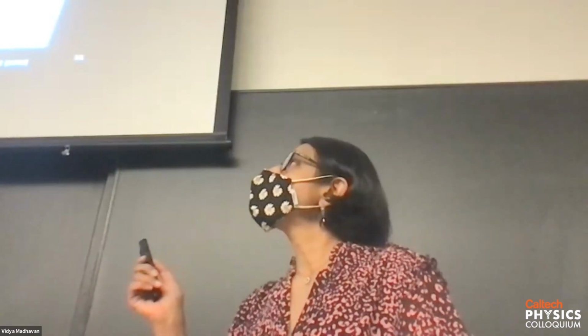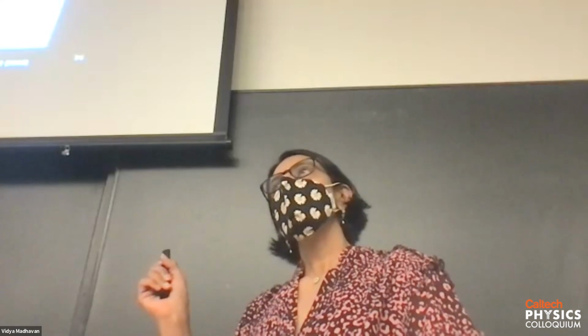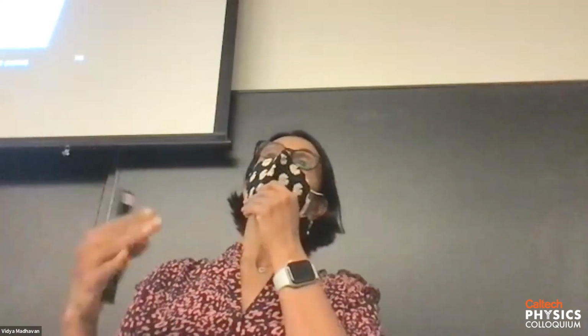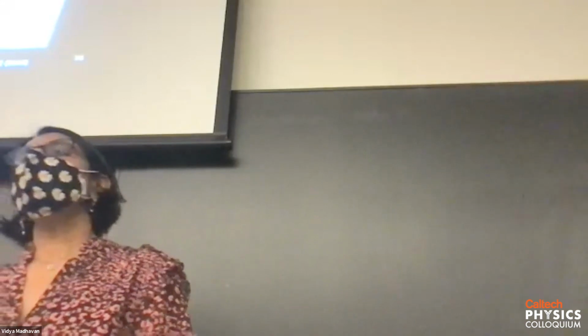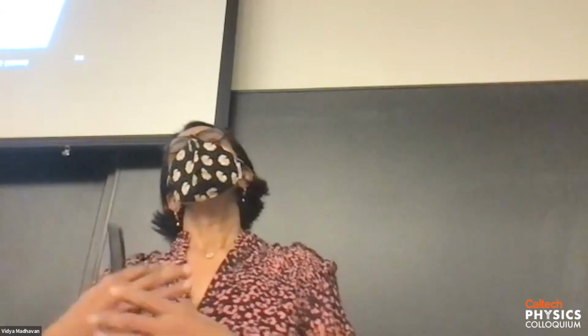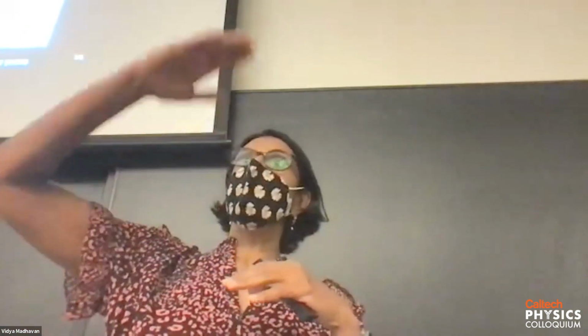But one thing I do want to say though. This material has a mixture of normal vortices where you have half integer spacing and these Majorana bound state vortices where you have integer spacing. You see both in the same system. So it cannot be just an S-wave superconductor. Then you might ask, why don't all vortices show Majorana fermions? And they attribute that, and we have all seen this, there's a huge amount of spatial inhomogeneity in the gap magnitude. And also the position of the Fermi energy with respect to that Dirac surface state moves a lot.